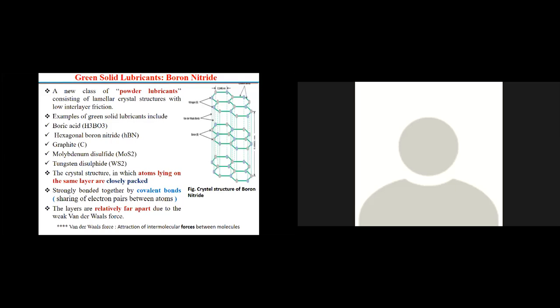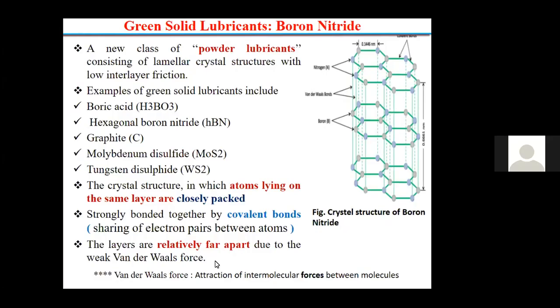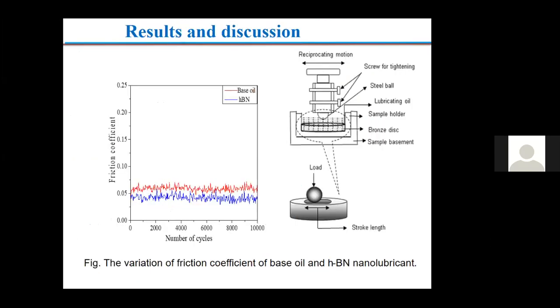In this particular experiment we have used boron nitride. This is the crystal structure of boron nitride. You can see the crystal structure in which atoms are lying on the same layer, closely packed, strongly bonded together by covalent bonds. The layers are relatively far apart due to van der Waals force. This is the beauty of this boron nitride crystal structure. So this boron nitride nanoparticle was used for this particular experiment.